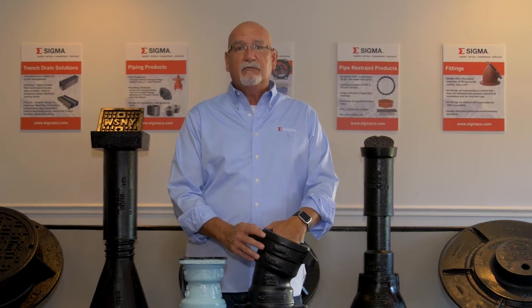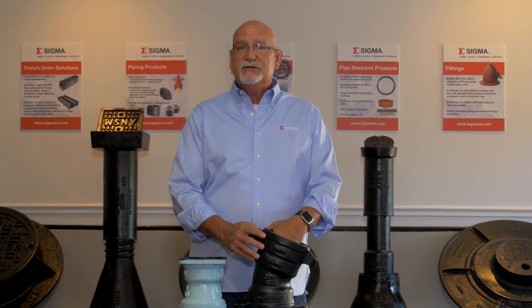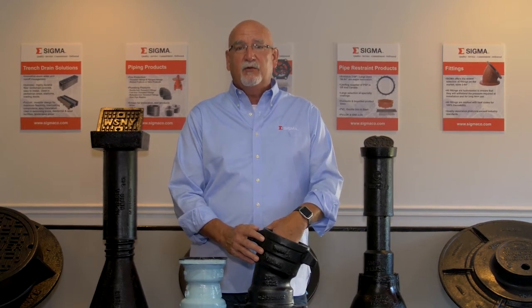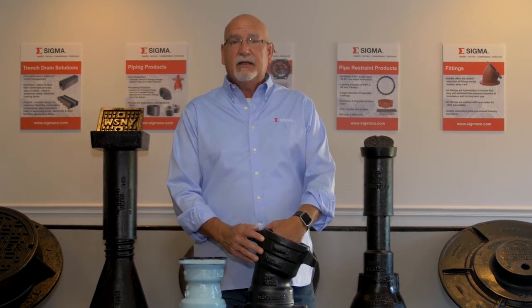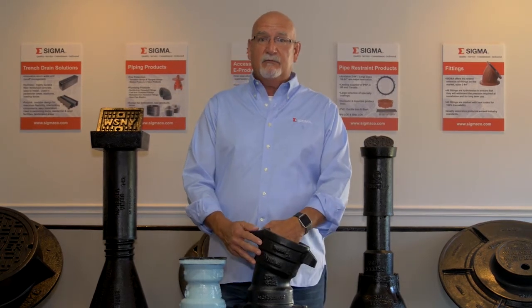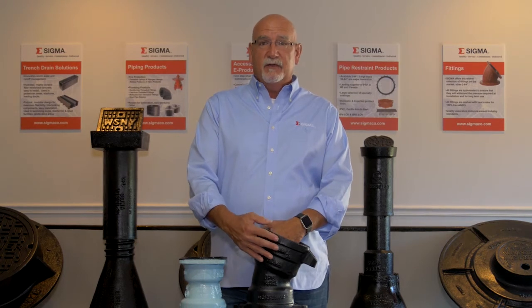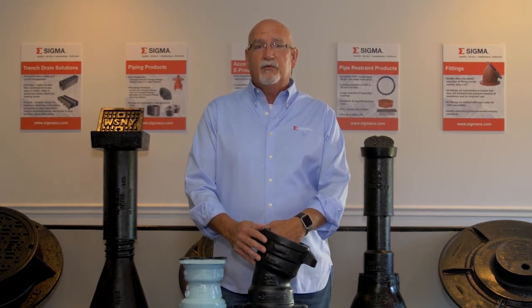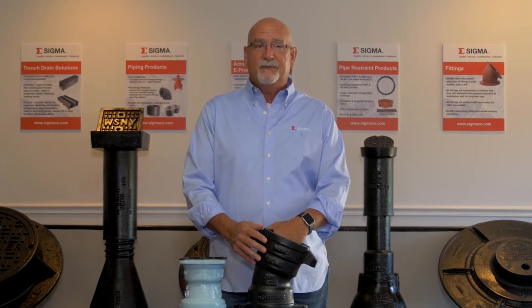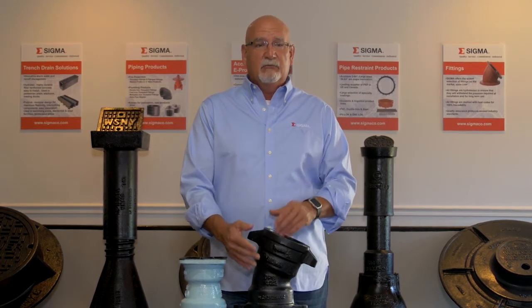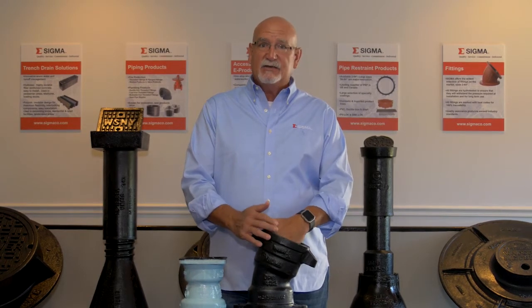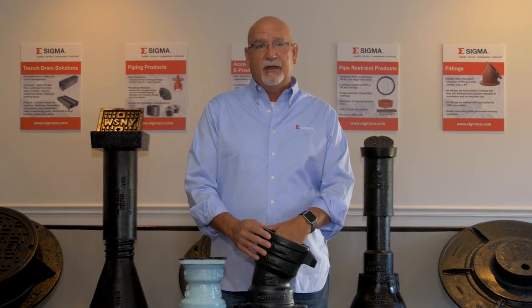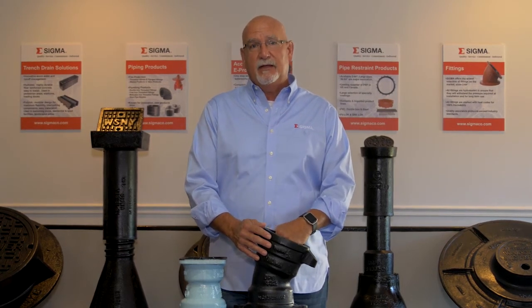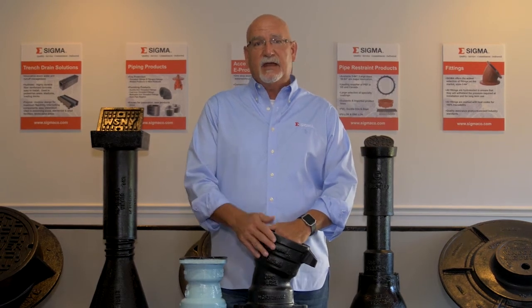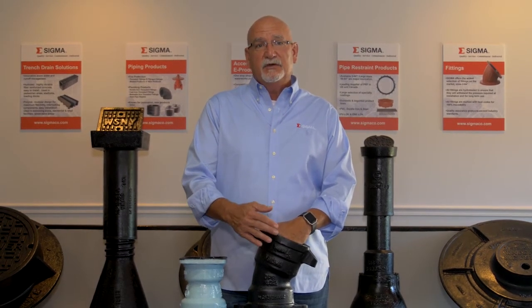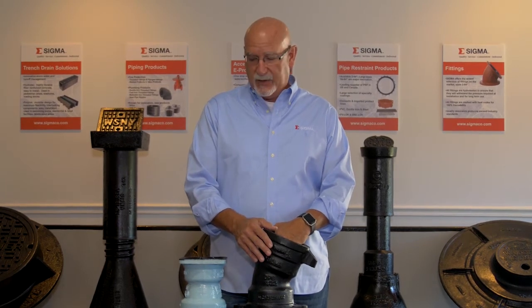So the cement is the most common lining, which is, again, also a coating that we find on the inside of fittings. The reason that it doesn't look like cement is because we paint it with the same black asphalt NSF material that's on the outside of the fitting to control the rate of curing of the cement so that it doesn't crack. So the reason that a standard fitting is black outside and black inside is because we use an NSF approved black asphalt paint to control the curing rate of the cement, and it also is in this AWWA standard for the material to be used on the exterior coating as well.